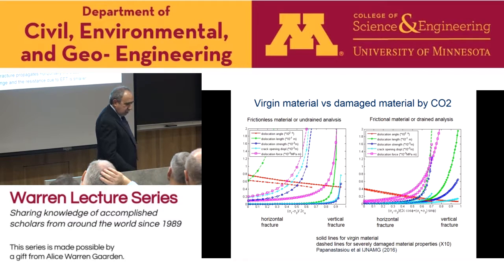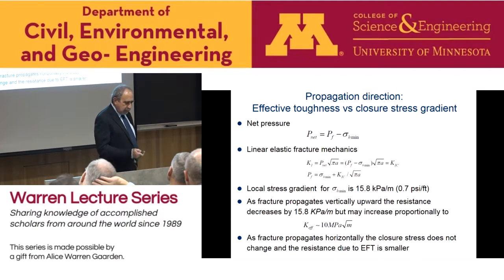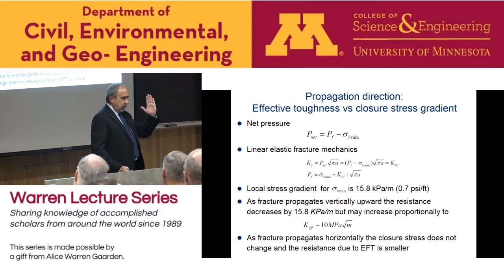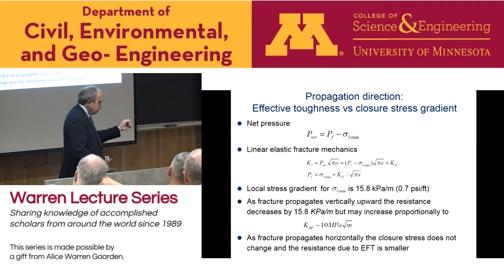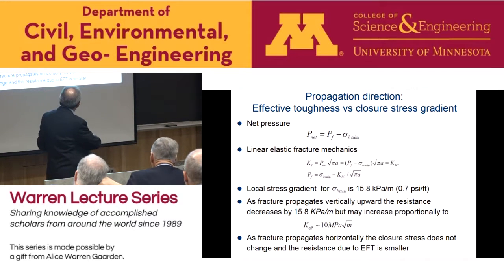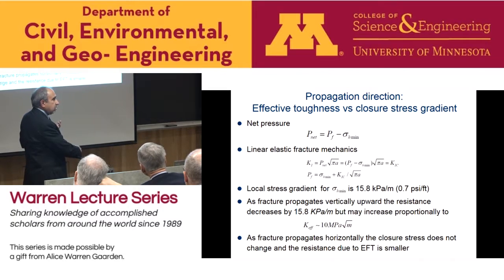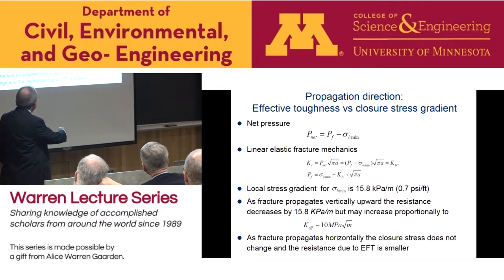And of course, in the oil industry, when you make these discussions that the fracture will propagate horizontally and not vertically, they look very strangely at this suggestion. They say that if we propagate vertically, the closure stress decreases. So the fracture should go vertically and not horizontally. Horizontally, the closure stress doesn't change. And I tried to write down some simple equations to see the comparison, okay? So the net pressure is, by definition again, pressure in the fracture minus the closure stress.